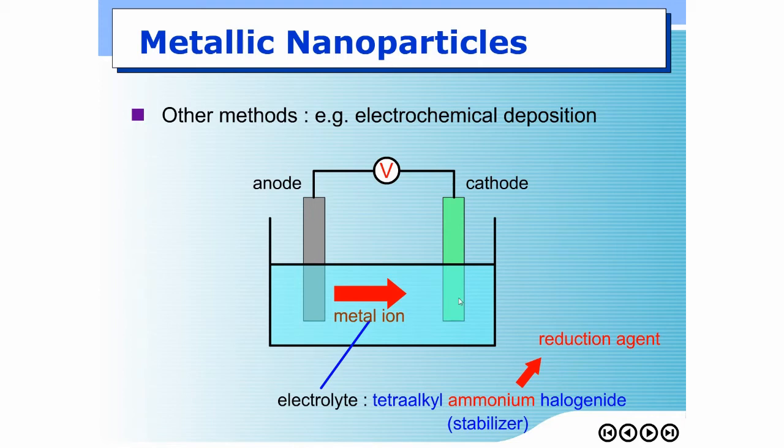But in this case, if we have a reducing agent in between, before the metals reach the cathode, that means metal ions must swim through the reducing agent. So during the way, the metal ions would be reduced along the way, right? Forming metals with oxidation state of 0. In other words, nanoparticles would be formed along the way.